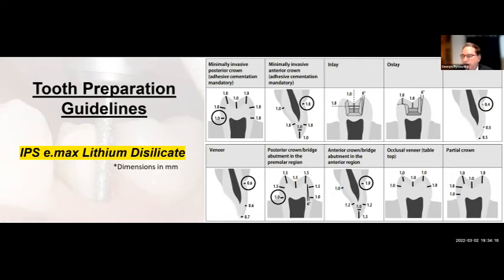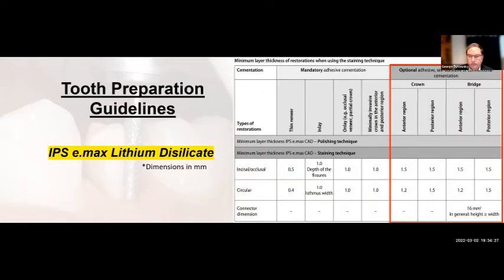For adhesive restorations like an occlusal tabletop, partial crowns, or 3/4 crowns, it's a millimeter with bonding. And again, if we don't bond, then we have to go thicker for those applications. That's repeating what we said before. If we're in the bonding category, we can reduce a millimeter. If we're going to conventional cementation, then it's about 1.25 for the reduction in these types of preparation guidelines.